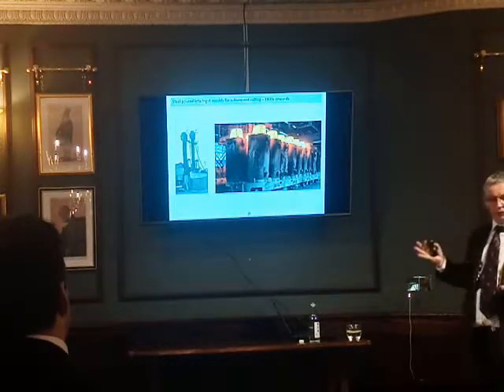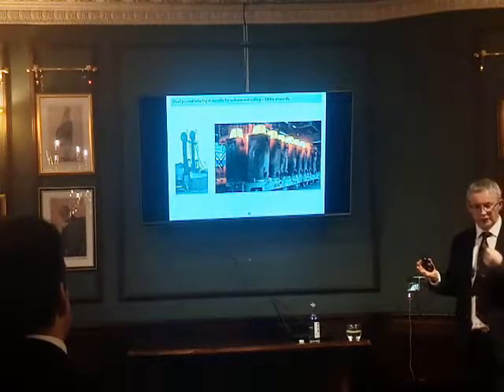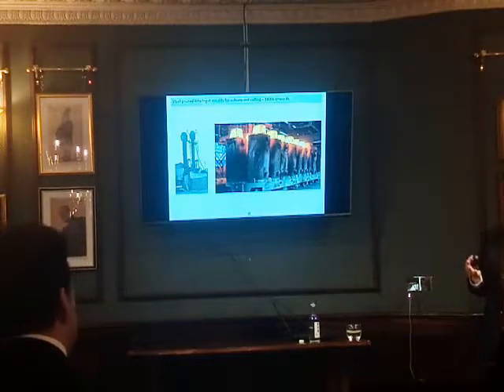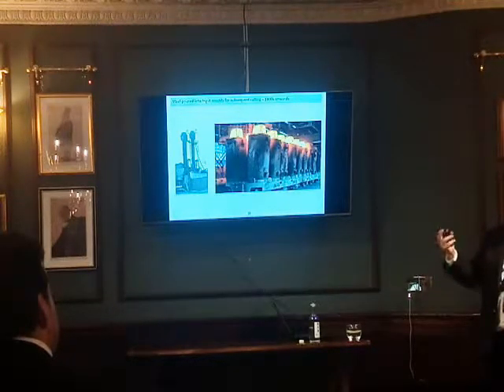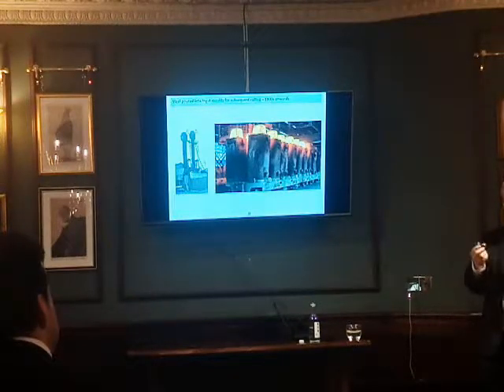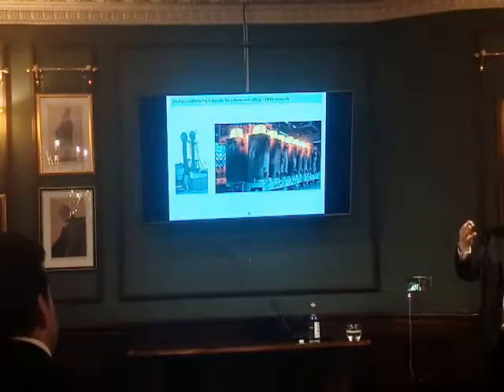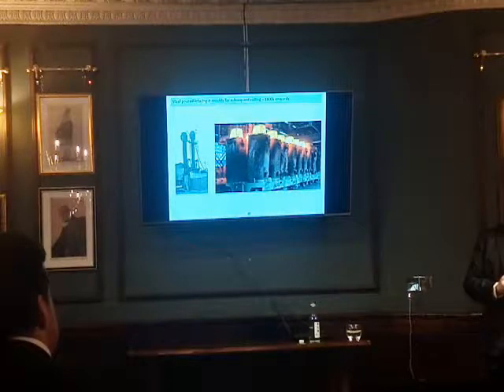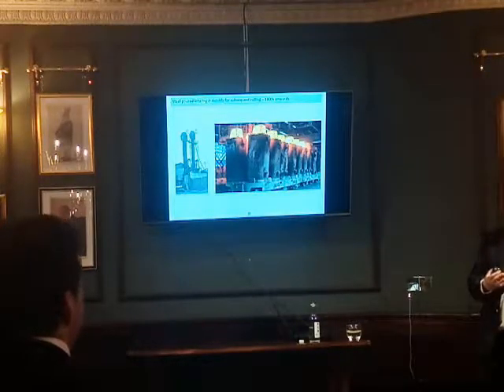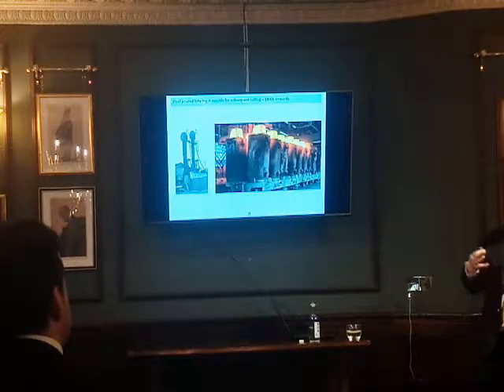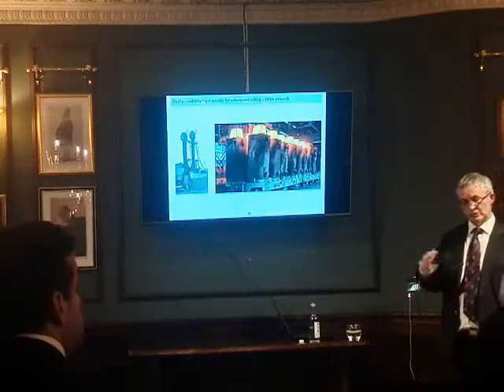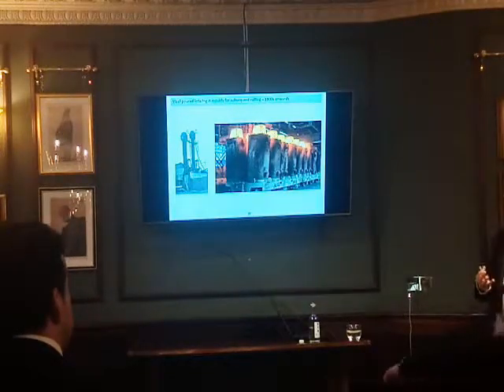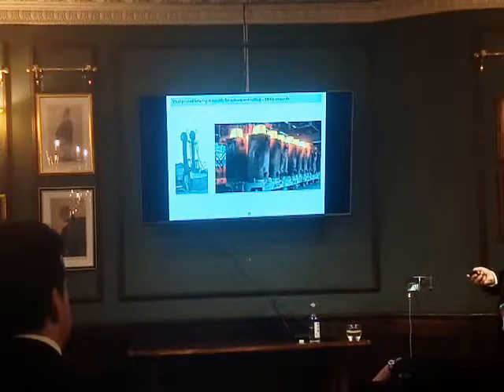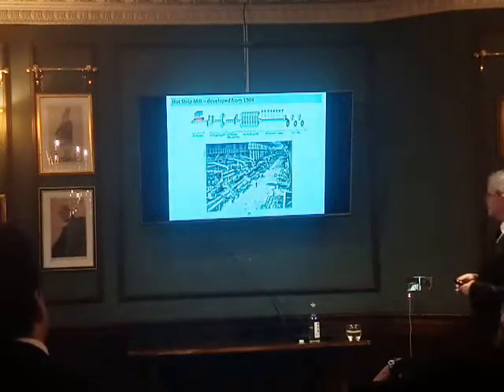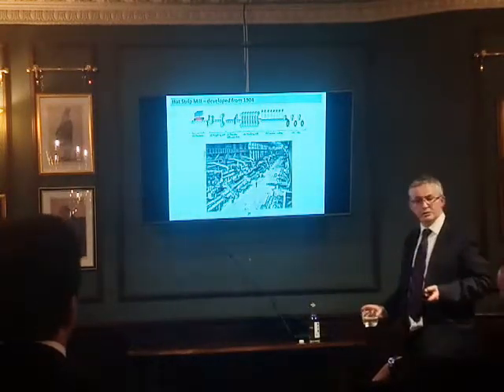The thing about ingot molds, they were perfectly fine. They worked very well, but there was a massive yield loss. Every time you made an ingot, all the running and rising and gating system that got the steel into the mold had to be recycled. And there was about a 25% yield loss every time you made an ingot. Perfectly good steel, it went back in the furnace, but you had to cool it down, and massive source of home scrap.